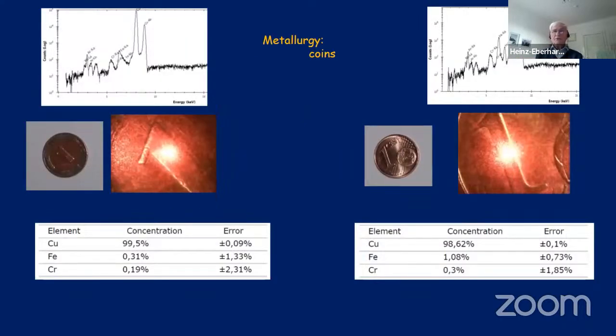To give you some examples, an illustration of 20 years ago, we had the Deutsche Mark, German Mark, and the penny in that system, the copper penny, was almost entirely copper, only a little bit of iron added to it. So these are the typical copper X-ray lines, the K lines coming out. Nowadays we have the euro. We lost a little bit of copper, just a little bit. It's only 98.6% now, roughly, with a little bit more iron content in there, as one can see here. But it's still more or less a similar amount of copper.